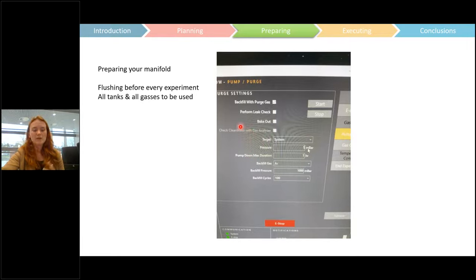We actually have two mixing tanks, obviously, on the manifold. We usually keep one for oxygen-based gases, and we have one for reducing gases. So sometimes we don't flush. If we're not running oxygen gases, we won't flush the oxygen tank, and we'll just keep the reducing tank, or vice versa. But realistically, I flush all of these every single time, as much as I can get away with before the experiment, because it makes a huge difference to the success rate in my experiment.